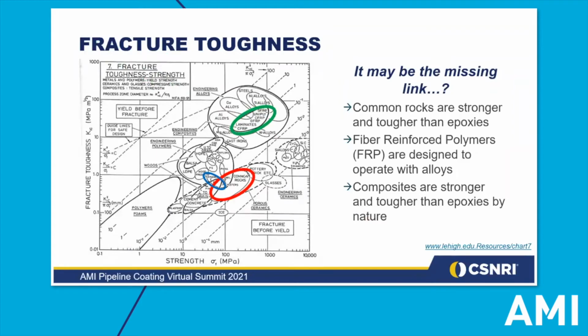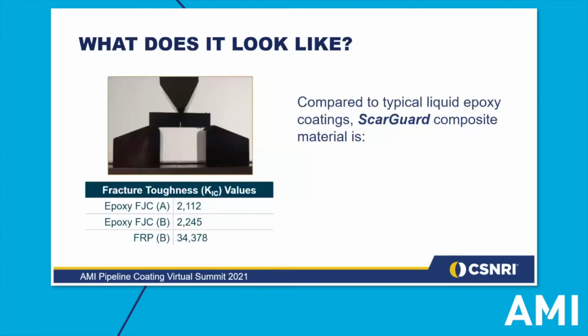And right in the center of that circle is the GFRP, or glass fiber reinforced polymer. While Lehigh University publishes this graph online, we wanted to see if this property could explain why we've seen over a decade of superior results using composite materials as compared to standalone liquid epoxies. To perform the test, specimens were pre-cracked, then a tensile machine takes the sample to failure. The ability to resist fracture is calculated based on the results.